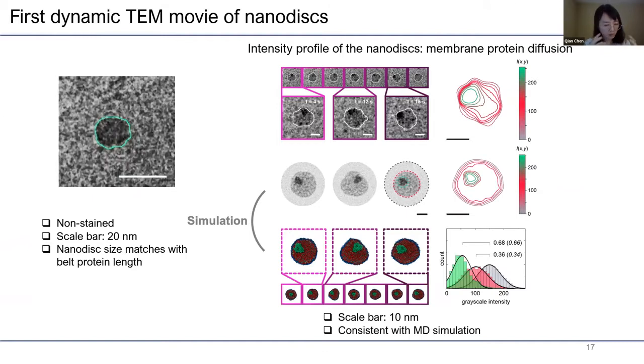The nanodisc was fluctuating because it's no longer frozen, and the size of the nanodisc matches really well with the prediction based on the belt protein length. If you look closely into the intensity profile inside the nanodisc, you can see those black features, which are the membrane proteins. In other words, we can check the motion and orientation of the membrane proteins inside the nanodisc, which is consistent with what we can see from MD simulation.